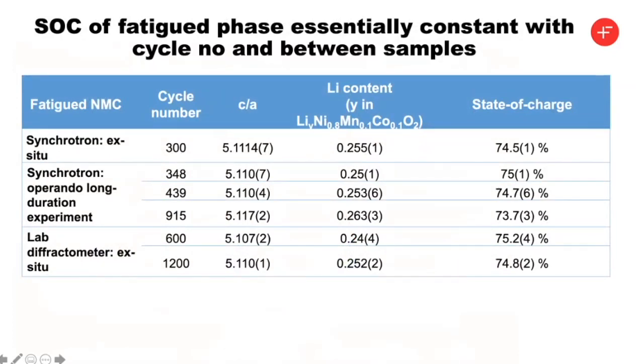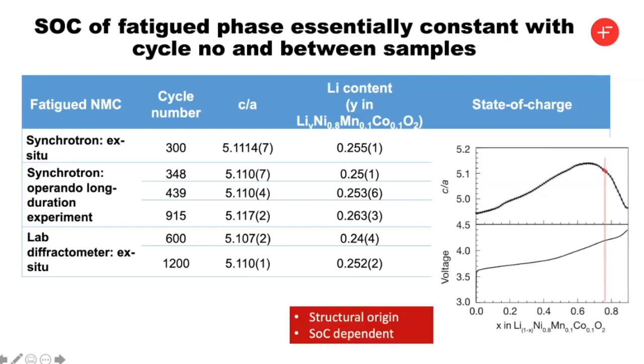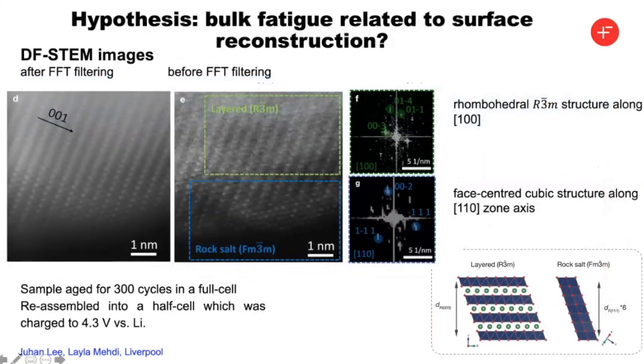So then let's examine this whole structural question. And so when we compared all of the data from the synchrotron diffraction, from the in situ, the ex situ, the lab diffractometers, we saw that this fatigued phase always ended up at the same state of charge. So basically, there was always about 25% of the lithium left in the structure. And this corresponded to the point of the C over A ratio just before the collapse of the C parameter. So this seems to be structural in origin, and the state of charge is independent of the method. The fatigued phase is always the same.